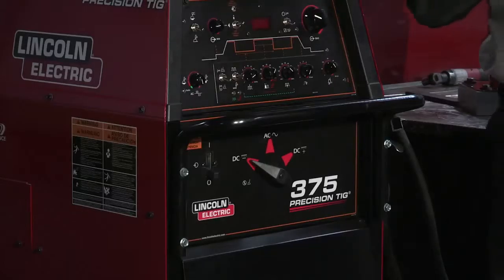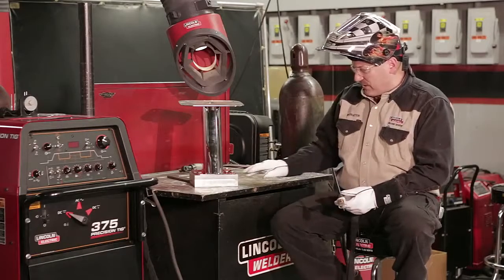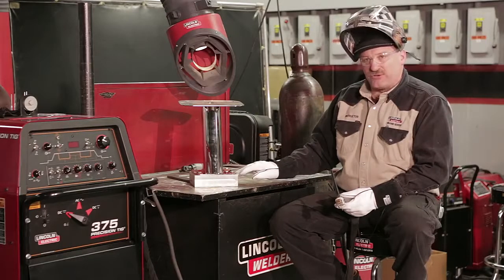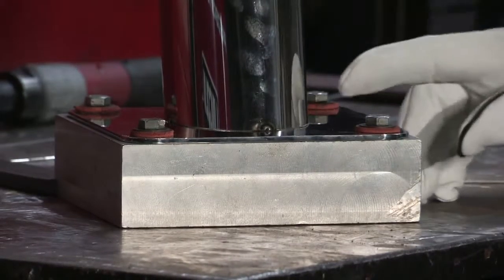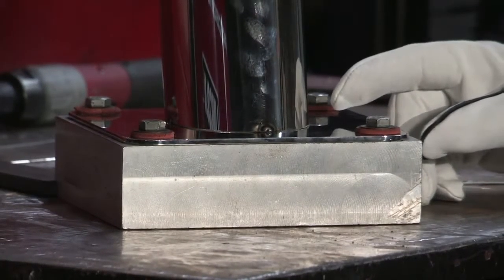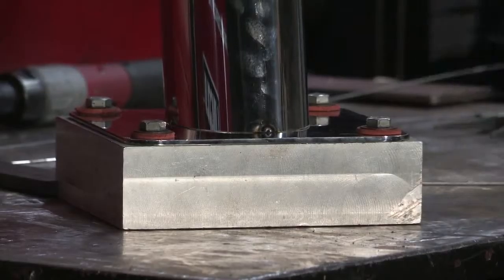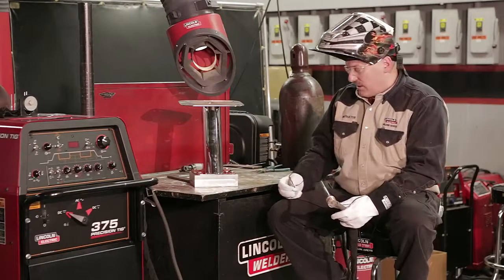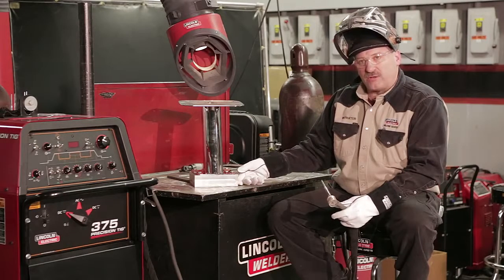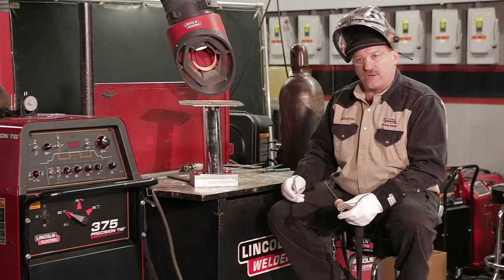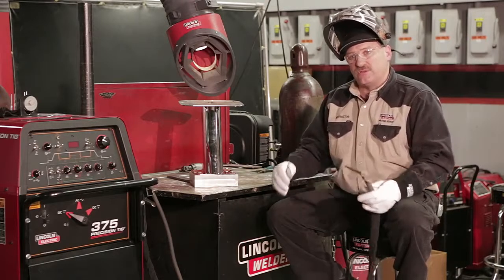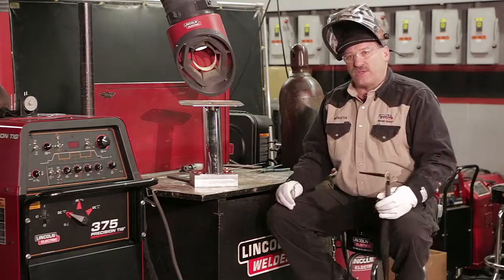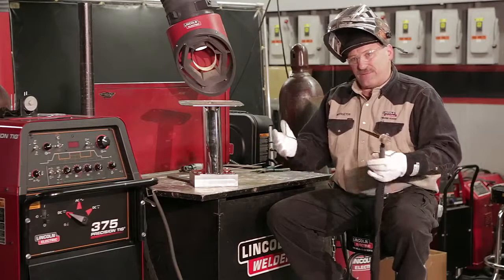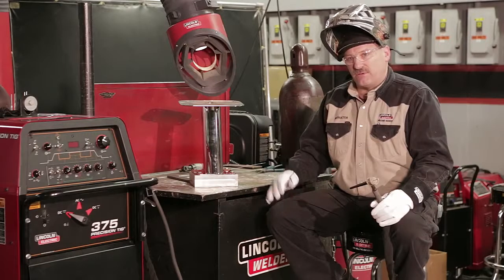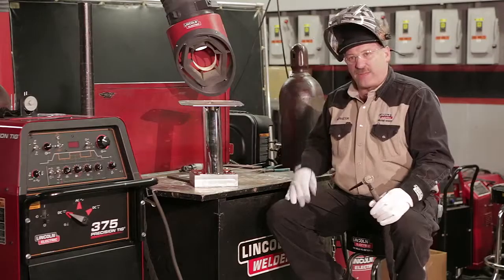torch. Precision TIG 375. Also what I've done here is I've bolted this down to a heavy aluminum block. This aluminum is about 60% as efficient as copper for sucking heat away from the weld. And also the fact that it's a rigid block, it'll keep that stainless steel from distorting. That's one of the problems you have with stainless, is it grows a lot when it's heated up, and when it shrinks back up, it distorts and you end up with not a flat base. I want a nice flat base.